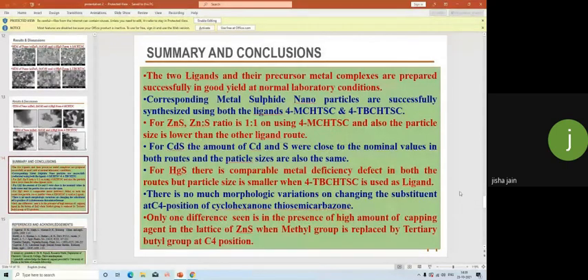Then summary and conclusions. The two ligands and their precursor metal complexes were prepared successfully in good yield at normal laboratory conditions. The corresponding metal sulfide nanoparticles were successfully synthesized using both the ligands, 4-methyl cyclohexanone thiosemicarbazone and 4-tertiary butyl cyclohexanone thiosemicarbazone. For zinc sulfide, the zinc to sulfur ratio is 1:1 on using 4-methyl cyclohexanone thiosemicarbazone, and the particle size is also lower than the other ligand route. For cadmium sulfide, the amounts of cadmium and sulfur were close to the nominal values in both routes, and the particle sizes are also the same.